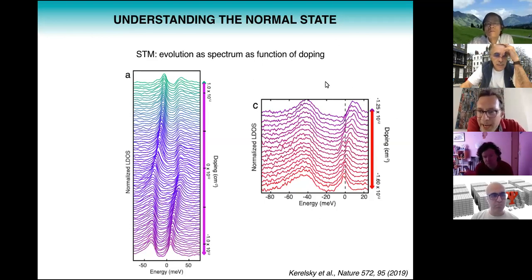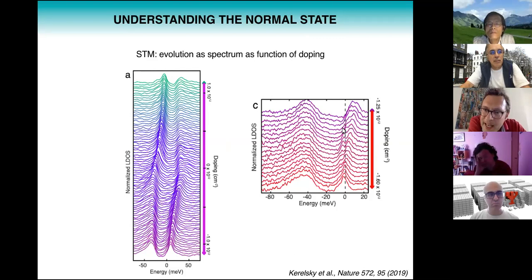Now, on the right-hand side is a zoom in, and what they are pointing out in this graph is that sometimes you actually see a breaking up of the Van Hove singularity, and you get a sort of double peak. And this double peak is actually interpreted as a signature of a broken symmetry state. So you could explain this double peak, for example, by the system becoming magnetic.